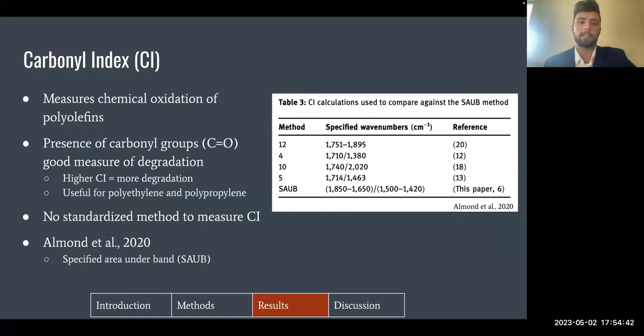So again, the carbonyl index has been used to measure chemical oxidation of polyolefins, such as polypropylene, over time. The presence of carbonyl groups means that there's a noticeable degree of degradation in the samples, and a higher carbonyl index indicates that the samples are more degraded.